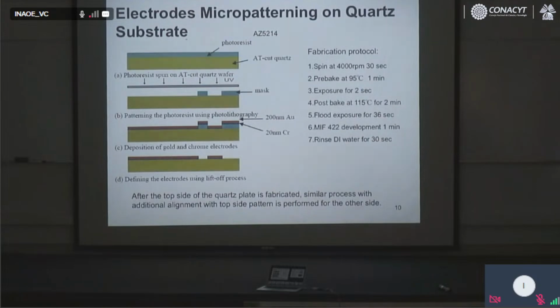The regular mask will be like $450, the one on the glass, the plastic MEMS mask. And then we deposit a very thin layer of chromium and gold, one on top of the other, and then we remove the photoresist. This is the classic lift-off process, and what we get is the quartz and the electrodes,